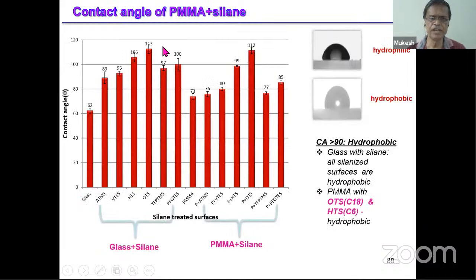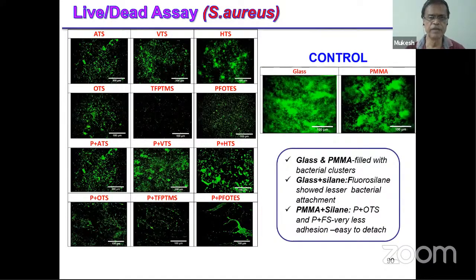Okay, so different silanes have different hydrophobic hydrophilic balance. Okay, that's called the contact angle. Contact angle gives you an idea about the hydrophobic hydrophilic nature. If the contact angle is very low, that means the surface is more hydrophilic. If the contact angle is very high, that means the surface is more hydrophobic. Okay, so we are looking at different silanes, how they prevent or enhance bacterial attachment, as you can see from these pictures actually.